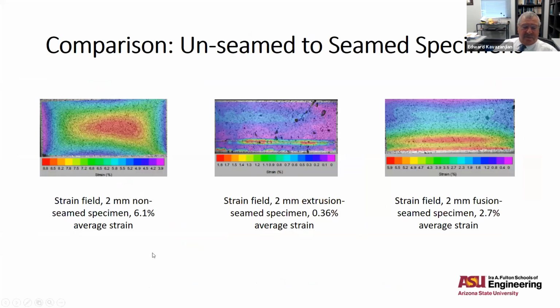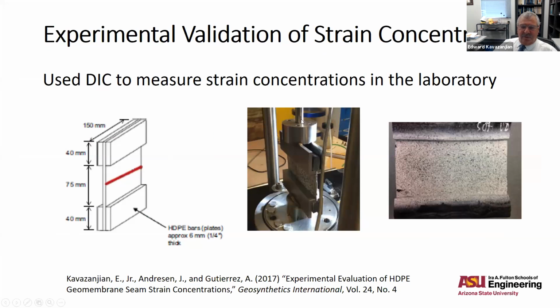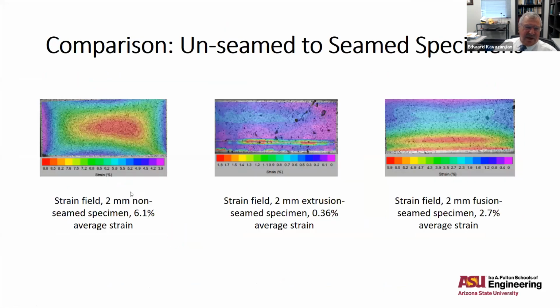Now, of course, that experimental setup with the grips and the limited length is going to induce some non-uniform strain concentration. So how uniform is the strain? Well, here's the strain field on a 2 millimeter plain specimen without seams that we stretched to an average strain of